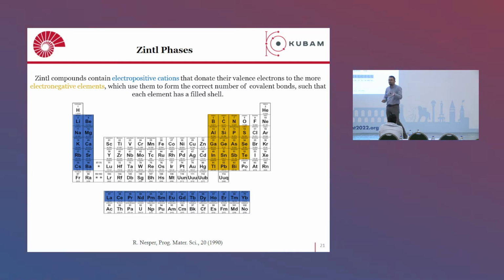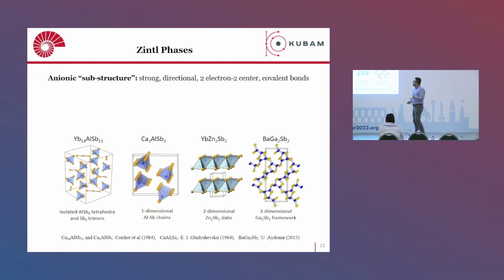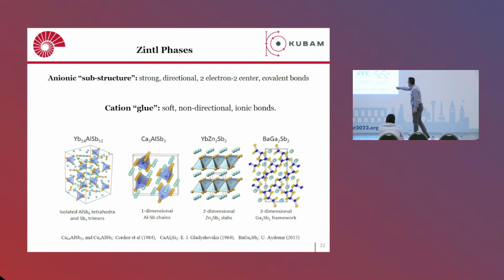And this electronic transfer leads to a particular connectivity of the atoms. The cation can be, again, alkali metals, alkaline earth metals, rare earths, even transition metals, and generally the anionic part is the p-block element. Now, these compounds are unique because they have an anionic substructure. You can see here different anionic substructures: zero-dimensional, one-dimensional, two-dimensional, layered-like, or even three-dimensional structures. They have strong directional two-electron, two-center covalent bonds, which accommodate in the cavities, as you can see, these blue atoms, the cations. These cations have soft, non-directional ionic bonds with the covalent framework. So they are kind of like composite materials on the atomic scale.